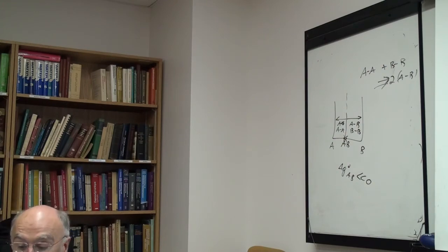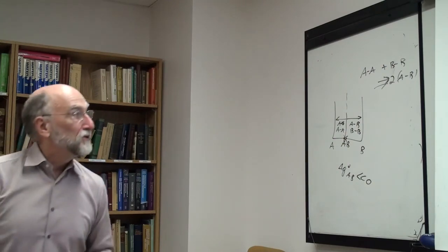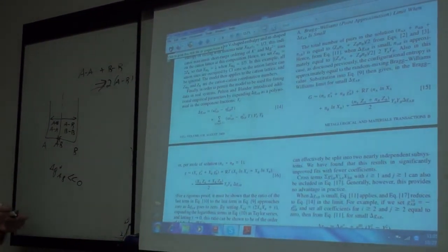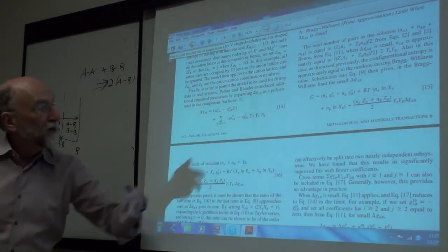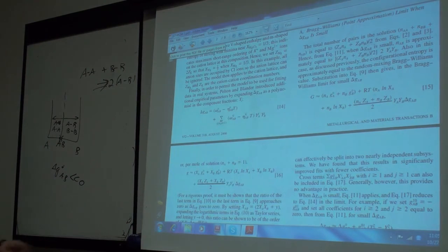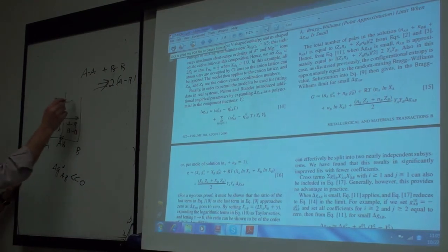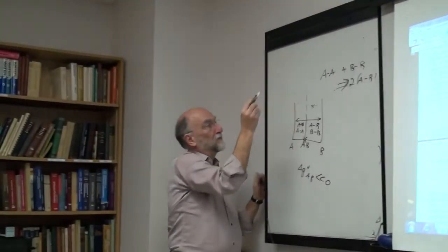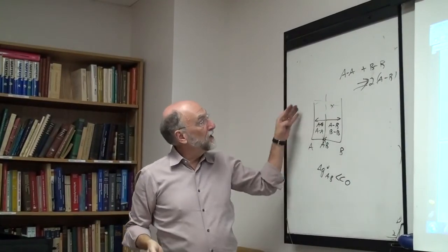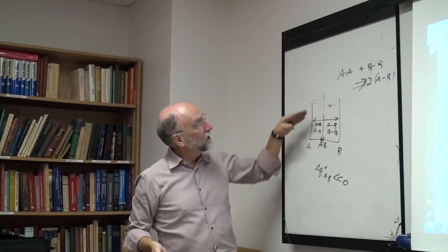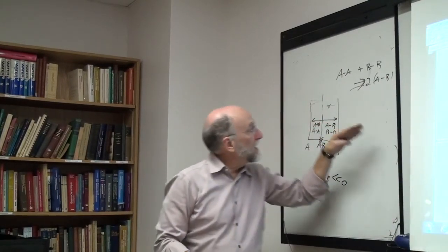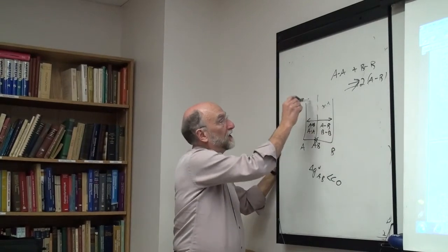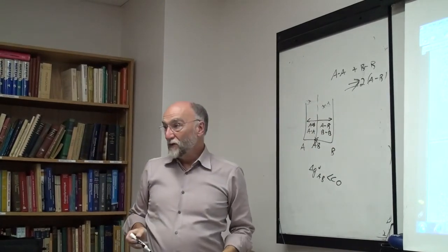You will find in many cases, say you're using a standard polynomial expression, that you decide to add a term in YA or YB to the delta G parameter because you want to fix up something on this side. You want to make your fit better on this side. But now you mess up the fit on the other side, because the YA and YB terms don't take into account anything about this. The terms in YA and YB apply over the whole composition range. So you want to change something here, and you end up messing up the system over there.